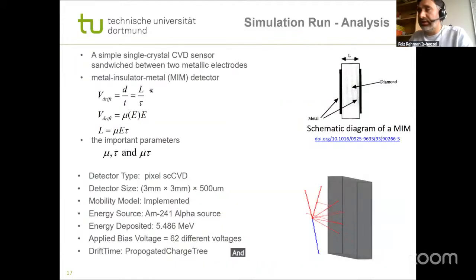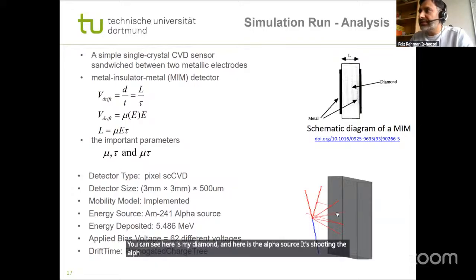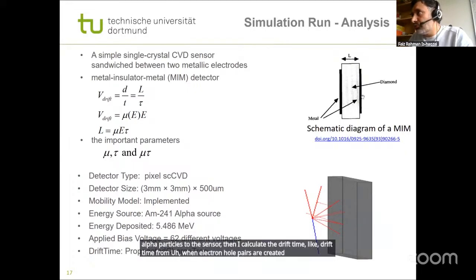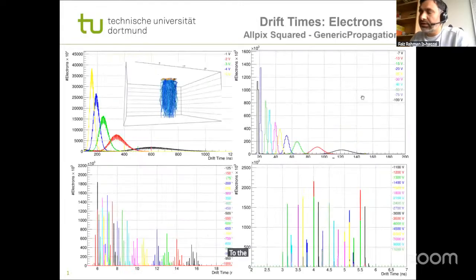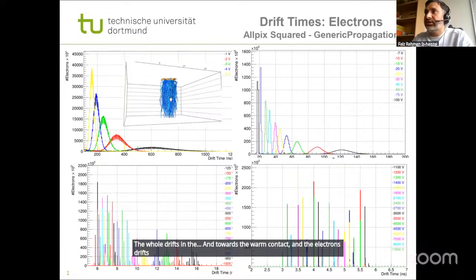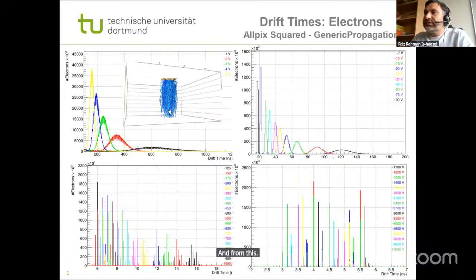For this I did this kind of simulation. You can see here is my diamond, and here is the alpha source, shooting alpha particles at the sensor. Then I calculate the drift time, from when electron-hole pairs are created here to when they move towards the other contact. When an alpha particle comes, it deposits energy in the sensor material. The holes drift towards one contact and the electrons drift to the other contact, and from this we can calculate the drift time.